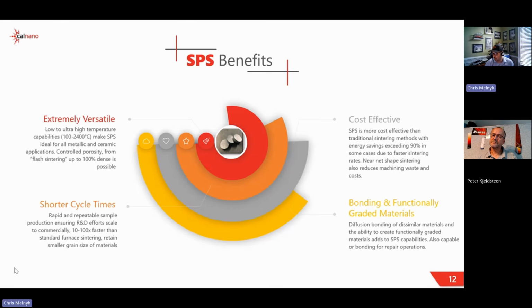And that comes from the shorter cycle time, the faster ramp rate, and then the faster cool down. So yes, it takes energy, but so does heating up resistive elements for hours and hours. Also, if you have a bigger system, you need to heat up the entire system, the walls and the furnace and the heating elements. Exactly. So you have a lot of dead weight with you that you have to heat and cool. And the time, right? Like I said, that really extends it. Absolutely, you're heating up this big box for all this time, whereas we just heat up the part, ideally, and the tooling around it, and that's it, and everything else is kept cool.